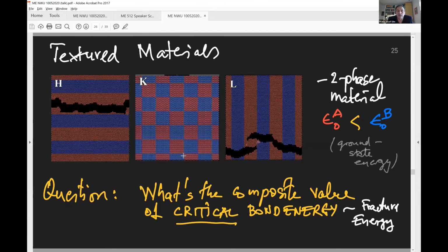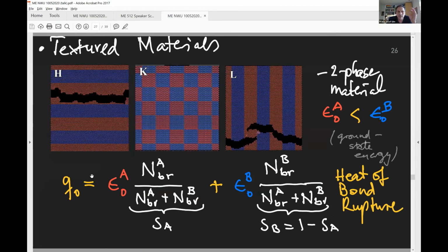And the question I want to address is, what's the composite value of this critical bond energy release rate? Now, to do this, I want to show you what this bond rupture ground state energy release rate, fracture energy actually means. It basically means that the number of broken bonds of phase A, over the overall bonds, have released the energy epsilon zero A, their base energy. Remind yourself that this base energy is in essence this value here, right? This epsilon zero A, the ground state energy. And then plus, for a two-phase material, epsilon zero B. So now we can really address the problem by means of simulation, determining NBRA and NBRB.